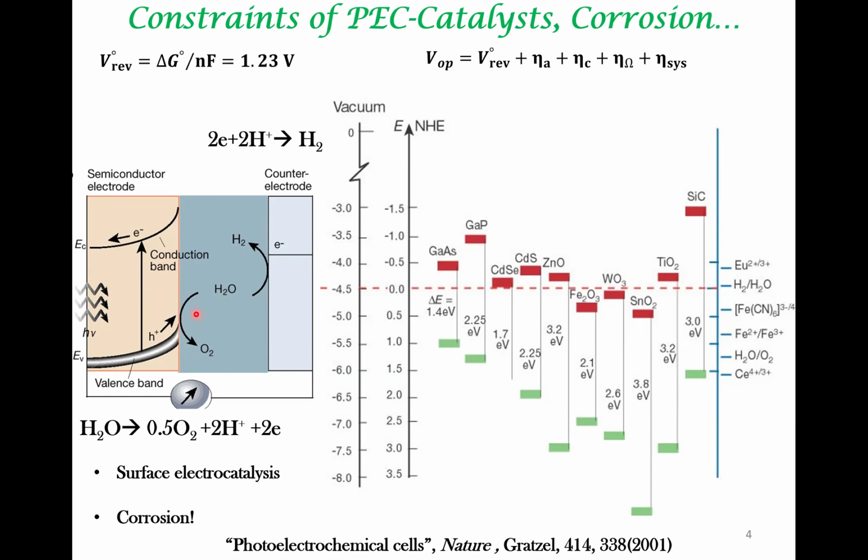First, if you don't use acidic or basic pH, the ohmic resistance in the electrolyte is significant. So you want to have, let's say, acidic pH for effective transport of ions in the electrolyte. So such an atmosphere has a lot of issues regarding corrosion. So many of the semiconductors that seem promising in terms of band gap and band edges are not stable in this medium.